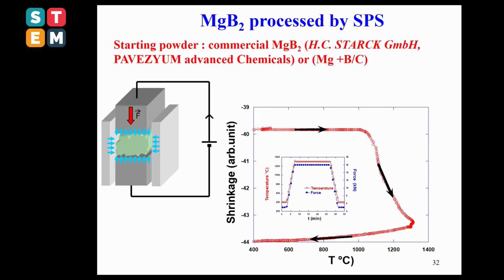density. The starting powder here is from H.C. STARCK GmbH, or from the Pavezyum company, the MgB2, or a mix of magnesium with boron or boron coating. Basically, you put our powder inside the die. By using SPS, we apply the pressure and current to densify it and record the shrinkage curve like you observe here. And the sample densifies quite well.